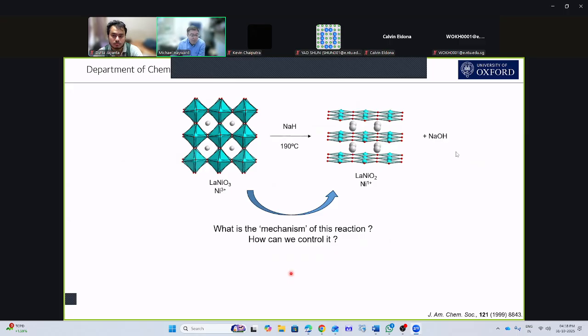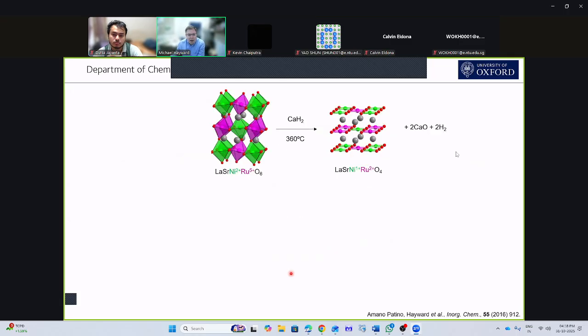We think a lot about the mechanisms of molecular reactions, but what about the solid state? Well, you can get some indication as to how the mechanisms of these reactions work when they don't work quite as you would expect. And a good example of that is this reaction here. So this is the equivalent oxygen extraction reaction, but from what we call a double perovskite.